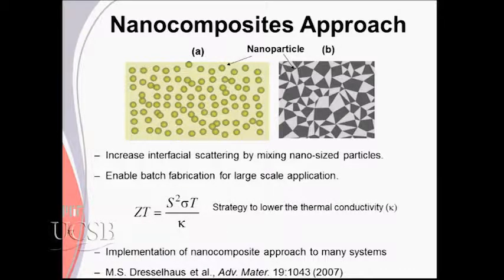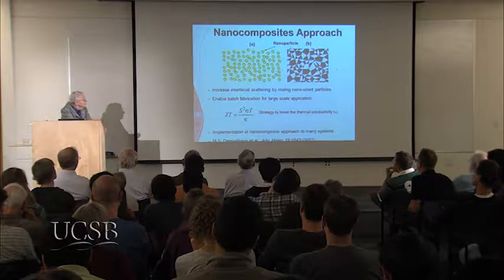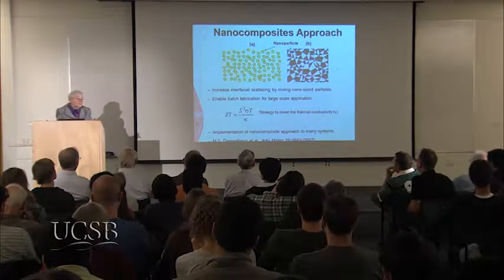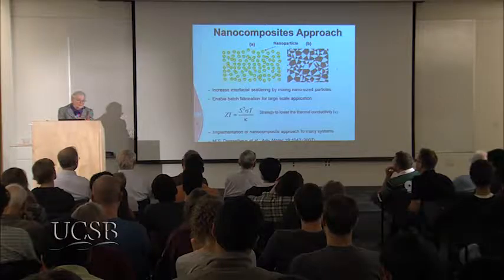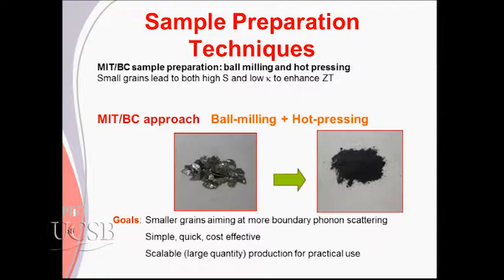So we put the nanos together. So here is nano in a bulk system. And here are nanos connected with other nanos. So nano A plus nano B. That's what the concept was. And our first experiments were to try to see if that concept, either of those, worked. And they both work. So you can do both. And there are many other approaches; what people are doing here is they have ordered nanos too. That's even better. But this was our original idea and what we went and did.